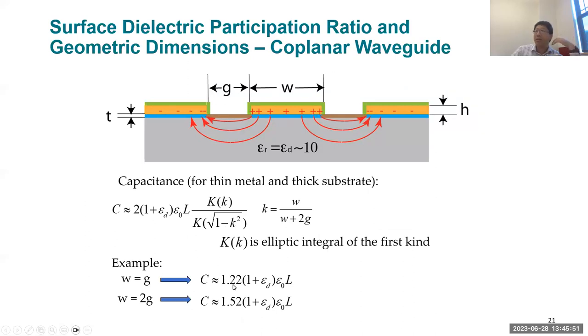So for things that are closer to the qubit geometry, you can think about, say, a coplanar waveguide structure. And in this case, it is a capacitor kind of in between the center pin here. Here, this is the substrate. Yellow here is your superconductor, your metal. And green, brown, blue, those are what I represent as these surface layers that may be lossy. Remember, the crystalline substrate is probably very good. On top, it's vacuum, it's perfect, but your surface may host the TLS.